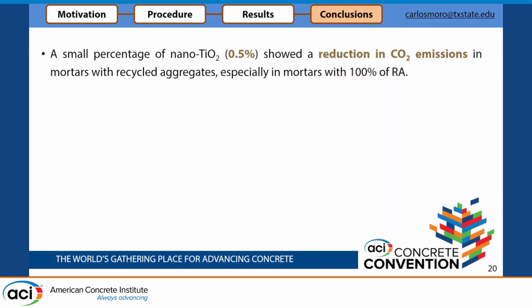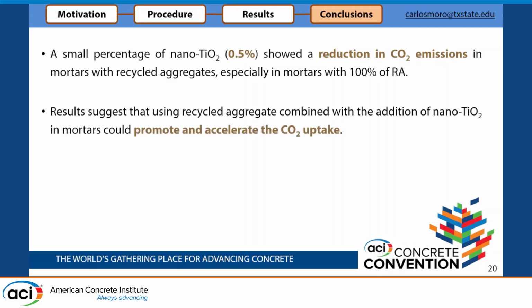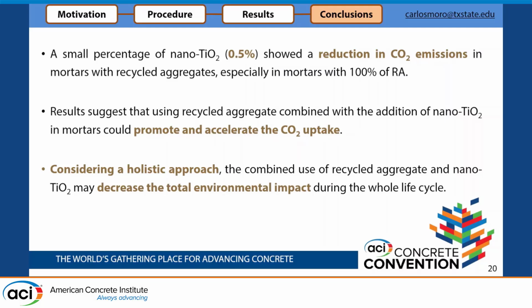So having said that, our conclusions were that the small percentage of nano titanium dioxide, that means 0.5%, shows a reduction in the CO2 emissions, especially in mortars with recycled aggregates. That means 50 or even going further, 100%. The results suggest that using recycled aggregate in combination with nano titanium dioxide promotes and accelerates the CO2 uptake. That means that we are uptaking faster, so we are not emitting that much to the atmosphere and the imbalance is lower. And also that if we consider the holistic approach and we consider all the beneficial effects that these nanoparticles could have, like the photocatalytic effect, the combination of recycled concrete aggregate and nano titanium dioxide may decrease the total environmental impact during the whole service life.